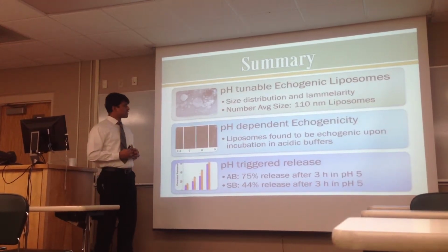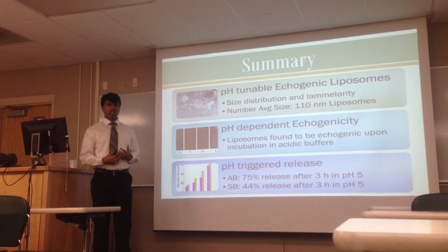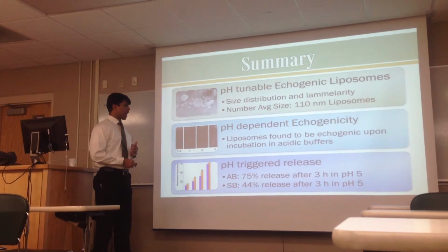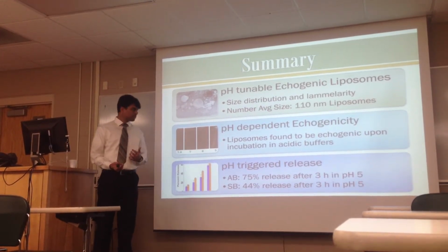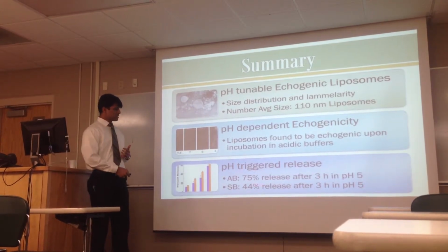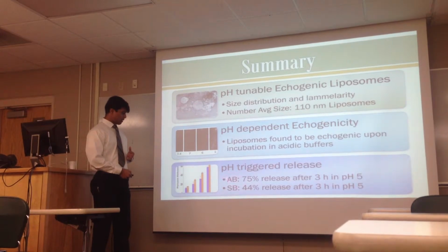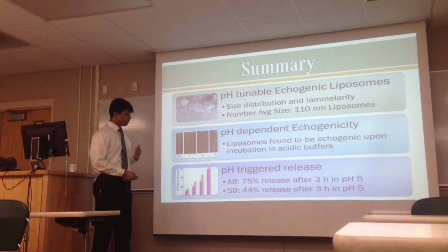To summarize the studies I have done until now, we have successfully prepared pH tunable echogenic liposomes with size around 110 nanometer, and the liposomes were found to be echogenic only upon incubation in acidic buffers. We got around 75% release with pH 5 buffers with ammonium bicarbonate liposomes, and with sodium bicarbonate liposomes we got around 44% release.